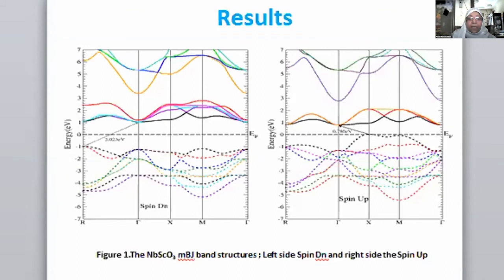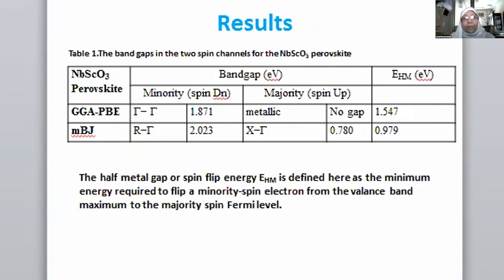So we could see now, we can show the values for the band gap here, and here, of course, it was not 1.6, it was 1.8, my mistake, in the spin down. And then, of course, we are having in also the K point values, the gamma to gamma has changed to an R to gamma gap. And of course, the new gap is opened at X gamma, where you're having 0.78.